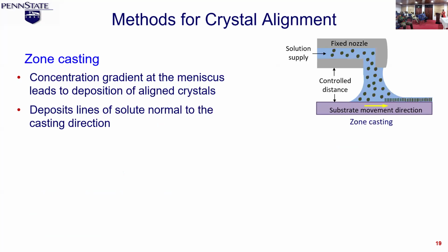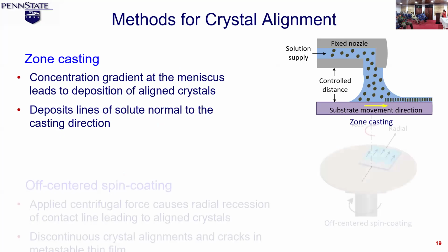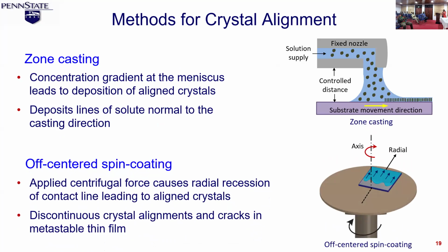Then we have zone casting. Zone casting is also one that has tried to orient these crystals. The disadvantage here is that the crystals are oriented in a perpendicular manner, and we typically want it more in a horizontal manner. And then the last type will be the off-centered spin coating. What it does is it uses surface tension and centrifugal force to drive the solution on the substrate outward as the substrate is spun on a plate. Right? And then crystals form on there. Again, the crystals here tend to be very thin and they are not very stable.